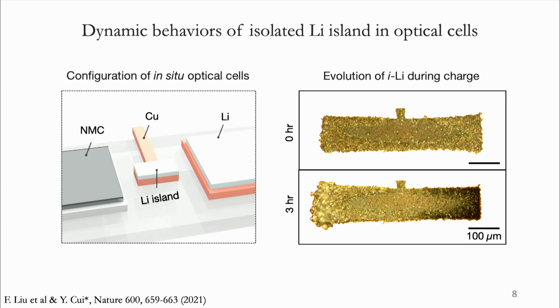But after a 3-hour charging process, one side of this lithium completely dissolved, leaving the black residue here, which is called solid electrolyte interface. And on the other side, we are observing a large amount of lithium deposited onto this island. So this phenomenon is consistent with our previous analysis, that one side is dissolving and the other side is depositing.